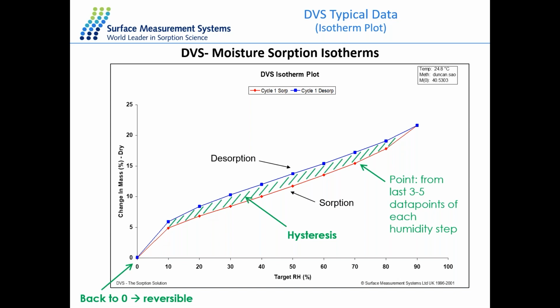The isotherm is very important to interpret the sorption mechanism from its shape, and there is some information we can get here. For example, at 90% RH, the change of the mass is about 20%, which is quite high and indicates a bulk sorption dominated mechanism, where the water molecules penetrate the surface and then go to the bulk of the material. It's also a closed loop experiment, with desorption going back to 0, which means it's a reversible process. The gap between sorption and desorption, called the hysteresis gap, also indicates desorption is a diffusion limited process. The water molecule penetrates, and when it's diffusing out it gives different kinetics, confirming the bulk sorption mechanism.